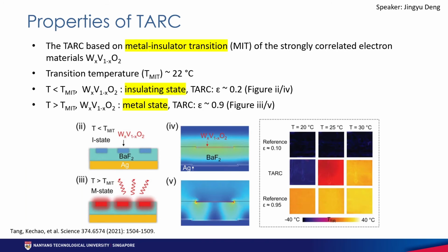Due to the special properties of the tungsten vanadium oxide, TARC also has very special properties. The tungsten vanadium dioxide has a metal insulator transition temperature, which is around 22 degrees Celsius. If the temperature is lower than the transition temperature, the tungsten vanadium oxide will show an insulating state, so the thermal emission of TARC is around 0.2. If the temperature is higher than the transition temperature, the tungsten vanadium oxide will show a metal state, and the thermal emission of TARC will be 0.9.